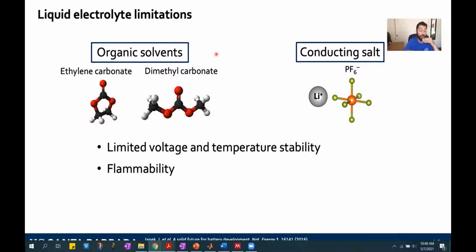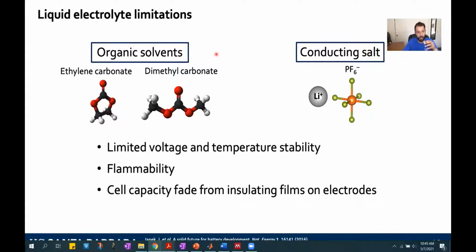On the other side is the flammability concern. So if you ever see videos of Teslas on fire on the side of the highway, or the whole Samsung Note fiasco, that's because the organic solvents were catching fire. Next, as the organic solvents sort of break down, they can create these sort of insulating films on your electrodes, which increase the resistance and will lower the amount of capacity you're able to extract from your battery. And finally, from the conducting salt is its toxicity. The fluoride anions that it contains can, when mixed with water, when mixed with air, can start to create hydrogen fluoride, and that is a really, really dangerous chemical.